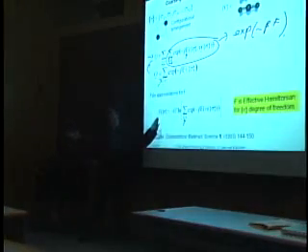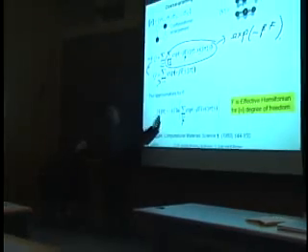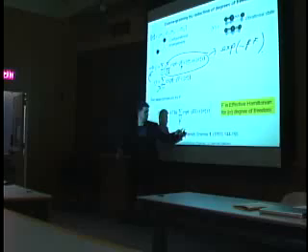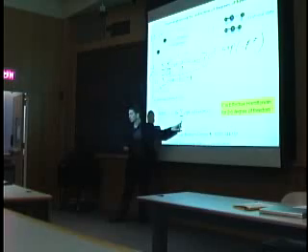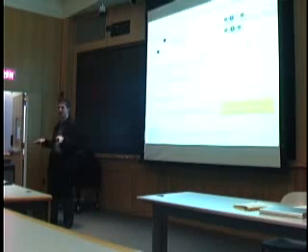I approximated this by the state in this ensemble with the lowest energy. If you think of this as a free energy, it is going to be a ground state energy plus an entropy term, with contributions from excited states. I've basically taken this just as the ground state energy in this ensemble, because I'm taking the lowest energy configuration that I can get by varying over this. And what is varying over this? The nus are the displacements from the lattice sites. So essentially I'm relaxing my system, letting it displace from the lattice sites, and I get the lowest energy state in the ensemble, and that's what I expand.